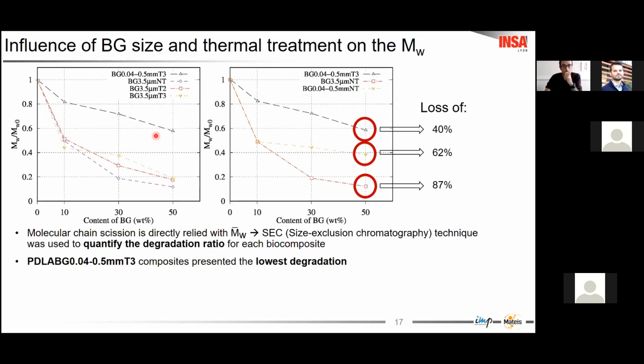For example, here, for the samples at 50%, we can see that with the smallest particle size and without thermal treatment, we had a loss of molecular weight of 87%.